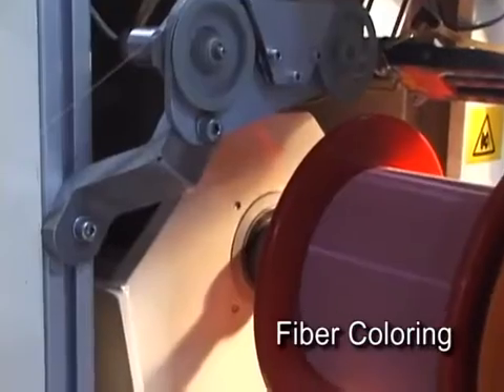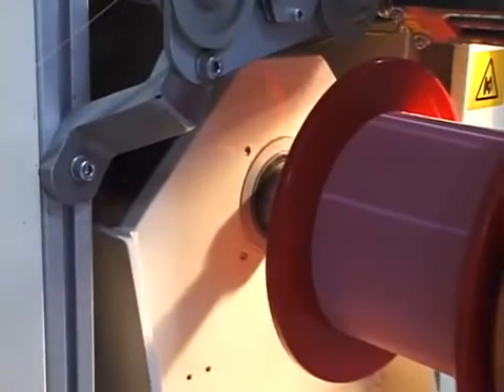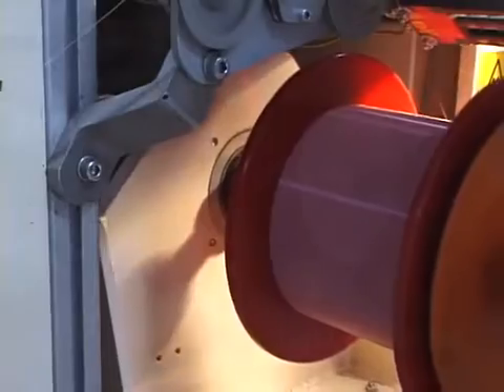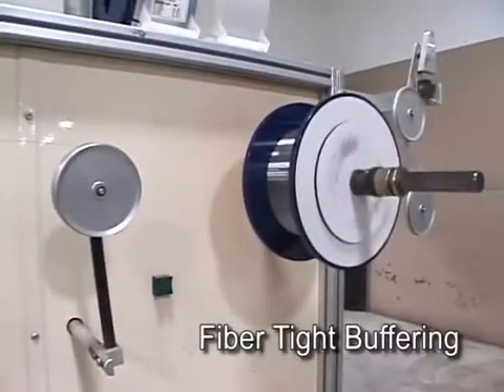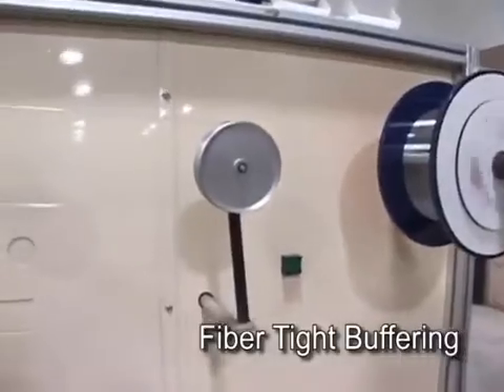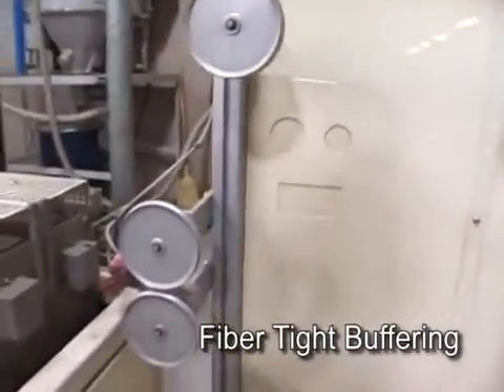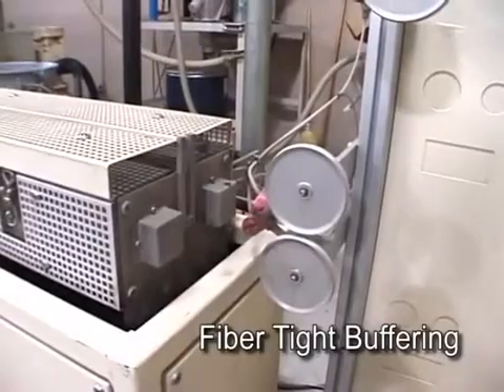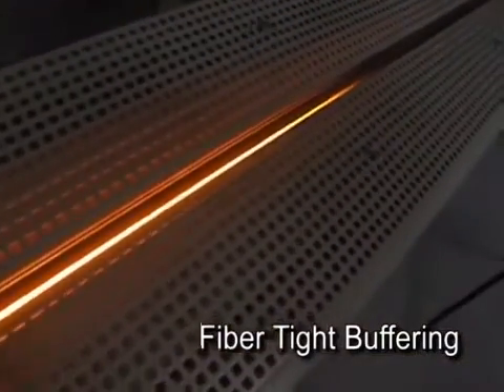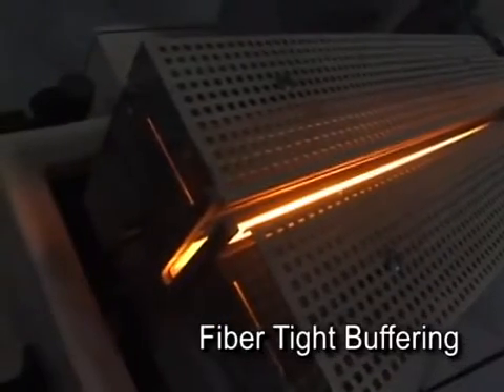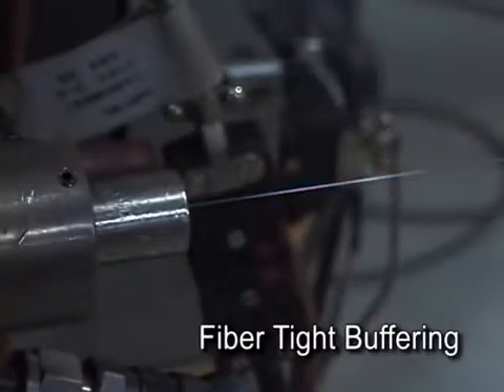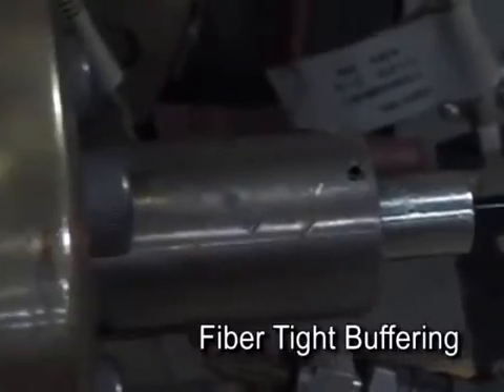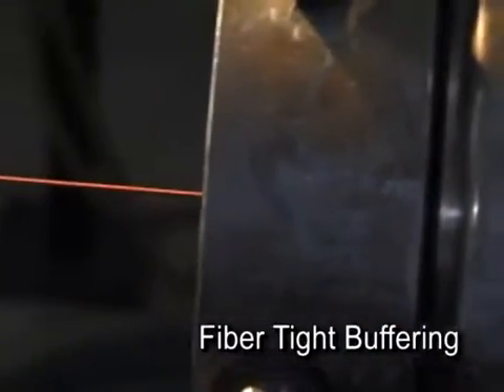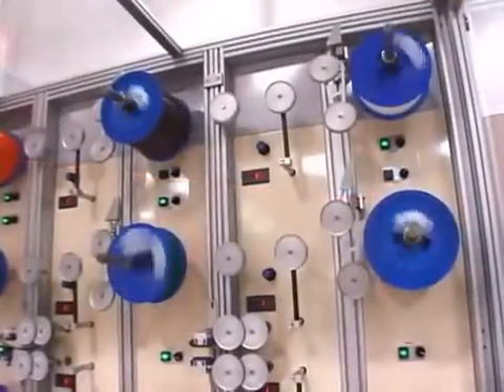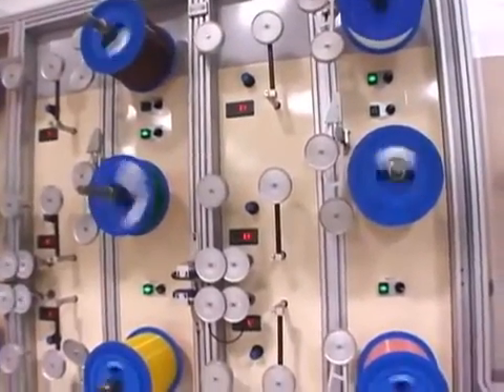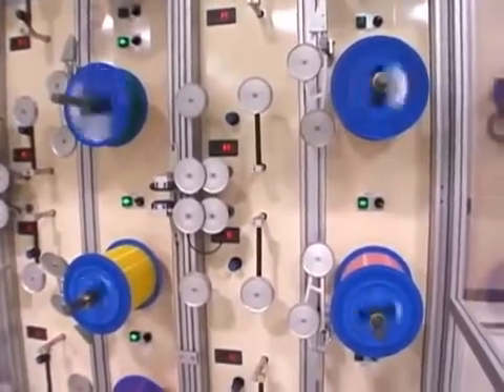The color-coated fiber is now ready to be put into loose tube or made into ribbon fiber. For tight buffer cable products, a colored PVC coating is applied that increases the diameter of the fiber from 250 microns to 900 microns. This process is called tight buffering, which, in addition to providing a color to identify each fiber, allows the resulting cable to be flexible, yet rugged and easily mated to mechanical connectors. For these reasons, the tight buffered cable design is the preferred fiber cable design for indoor cable applications. At this point, fibers destined for loose tube or tight buffered cable proceed to the sheathing or tubing process.